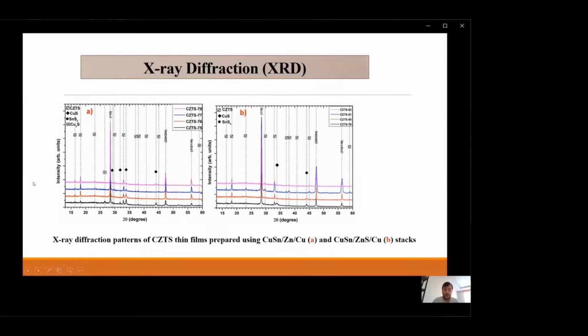Apart from the kesterite CZTS phase, as you can see, at low reaction temperatures, you can see some copper-based secondary phases occurred, and also tin-based secondary phases like copper sulfide, tin disulfide, and copper 2 sulfide. But here I want to draw your attention: as you increase the temperature above 550, you can see some tin sulfide also appear again.